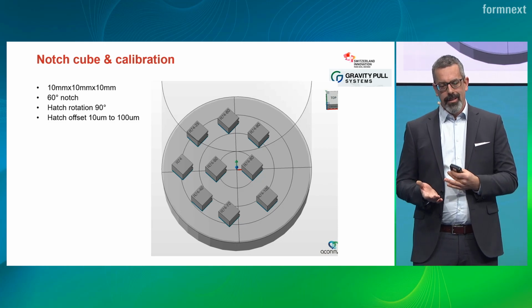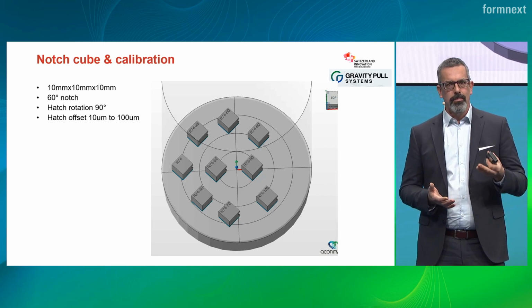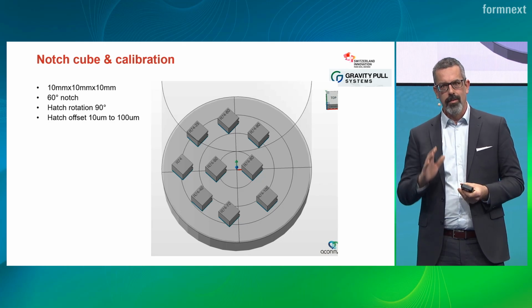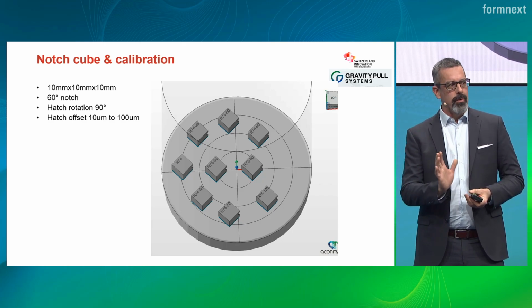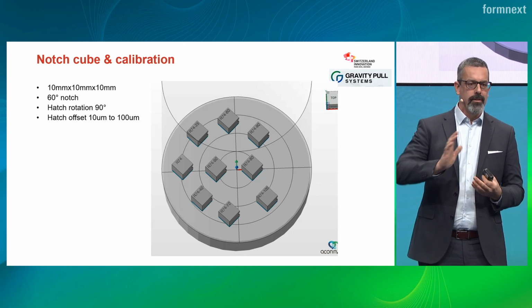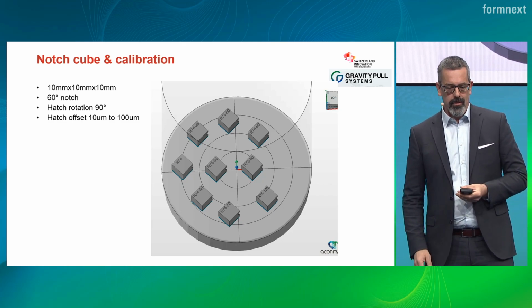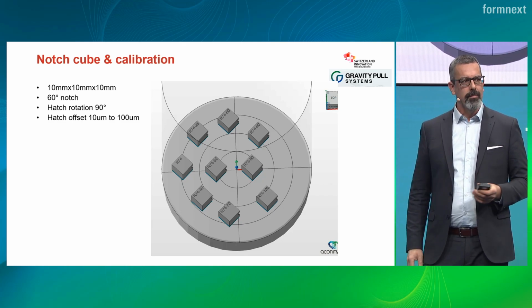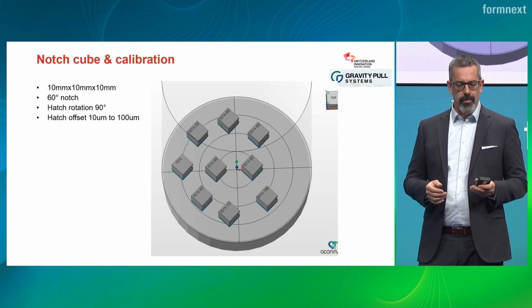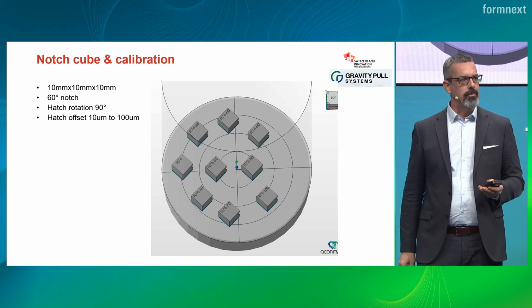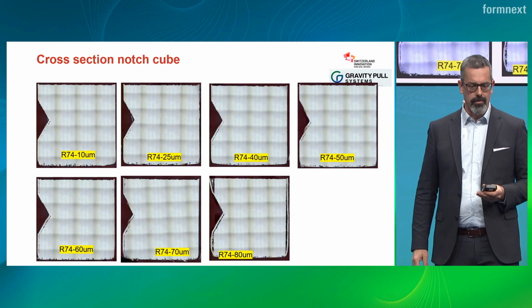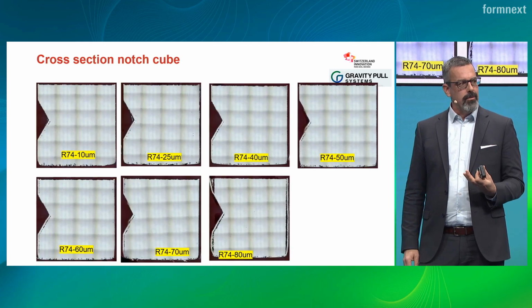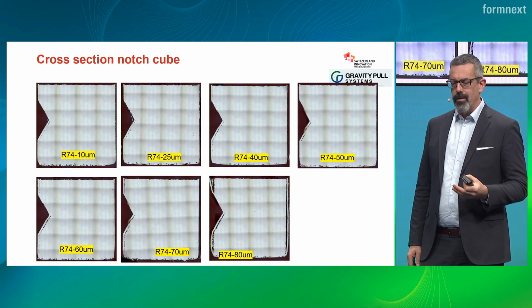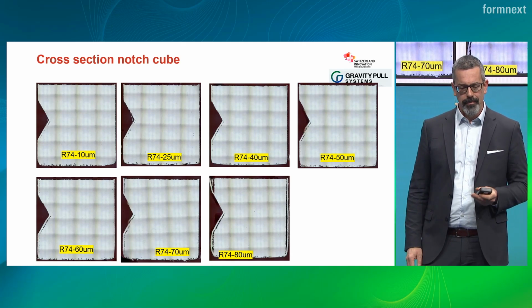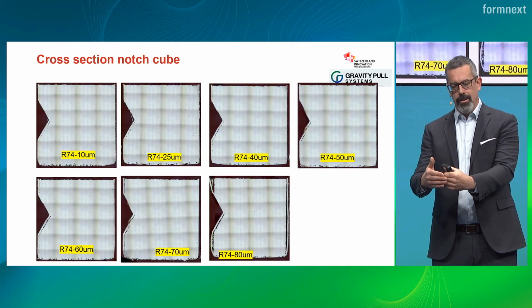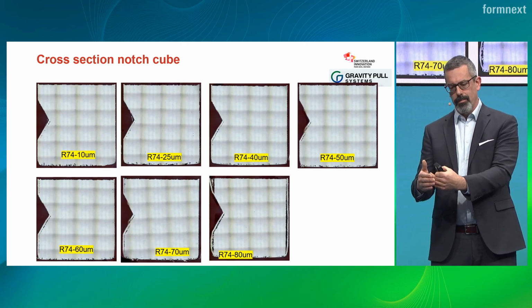The next geometry that we look at is a simple cube, but just added a notch of 60-degree angle, so we are always in the in-skin parameters, so we don't change to downskin or upskin parameters, but we remain in the same recipe. The hatch is now rotated by 90 degrees just to make any porosities more visible. And we vary the hatch offset. What you see here is cross-sections through this notch cube with different hatch offset, like offset of the hatching from the contour.